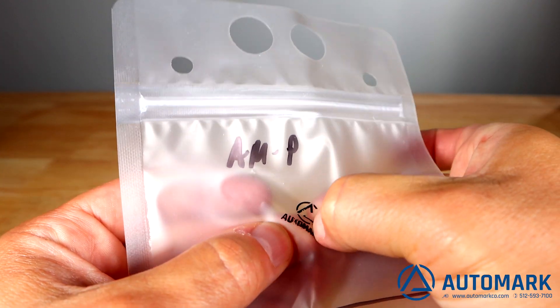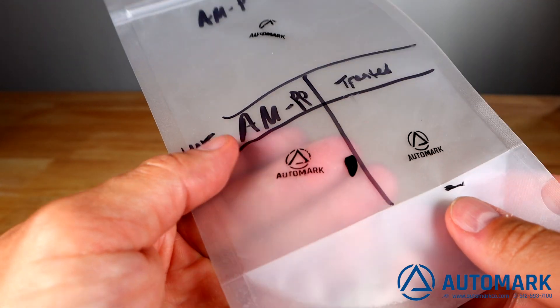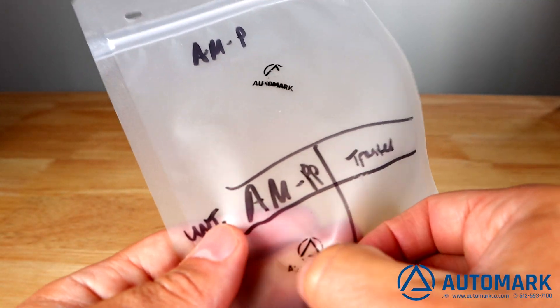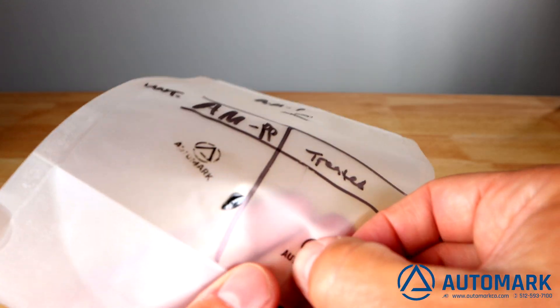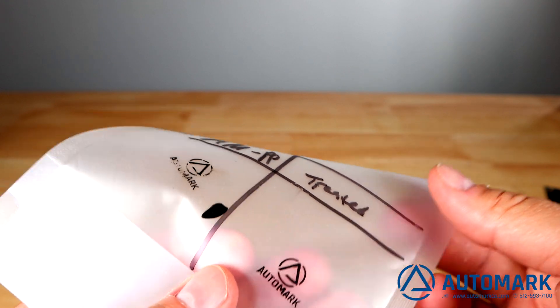Our test worked great. The AMP and AMPP inks are flexible, but notice the AMPP ink only works on the treated surface — the AMPP untreated area still flakes off. One of the biggest advantages of the AMPP ink line is that the shelf life is up to two years when stored properly.